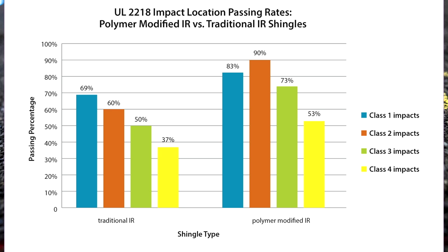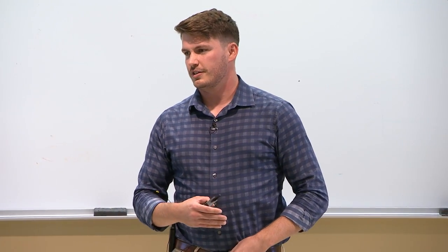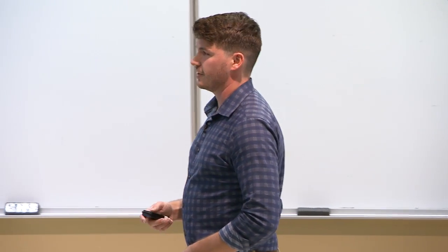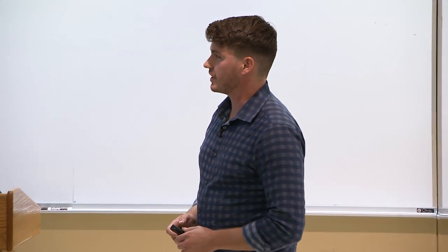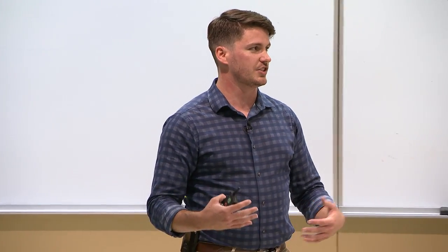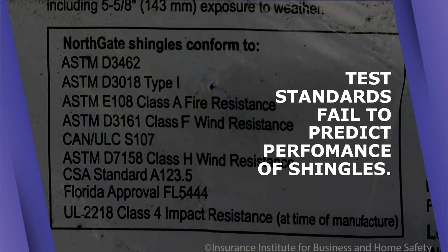So I want to look at class 4 impacts, the yellow bars here. For traditional IR shingles, only 37% of those tests passed. And for polymer modified IR shingles, 53% passed, right? And so when you compare these things with a relative performance metric, you see that they're not impact rated to the point where they'll always resist these hailstone impacts, right? And so getting off the pass-fail testing into more of a relative performance of material is the way that we want to go here. And so all this to kind of set the stage and say test standards fail to predict the performance of shingles, right?